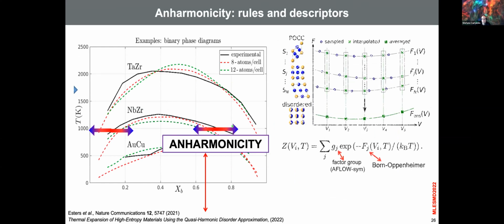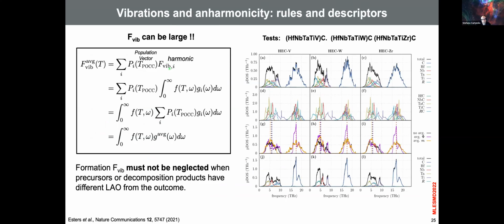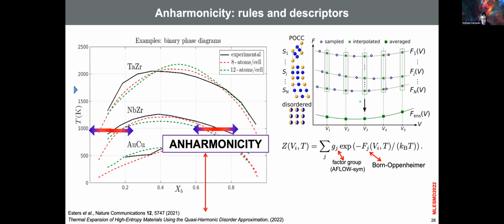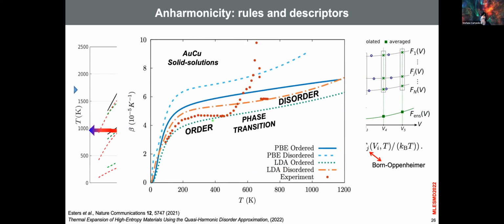It's even a little more complicated. Here you just need to calculate, remember, here you have the vibrational, the harmonic free energy. Now you can put the anharmonic free energy. In this case, you just change it as a function of volume. All right, you make an even more complicated convolution. You get, this is an article being submitted, you get the Z, the partition function, and you do all the derivatives, and you can get the thermal expansions. So you can get the thermal expansion of a disordered system with respect to the ordered ones.